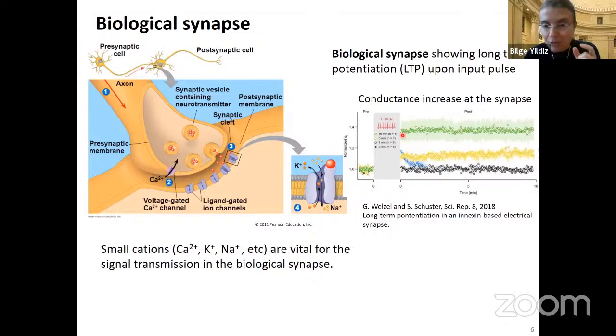So that is the green curve. The shorter that they send the stimuli, the weaker or even decaying behavior, so the loss of that strengthening, that's evident. So that's why we need to do many homeworks to learn a concept. You have to repeat to make it permanent and not to forget the next thing, right? So that's the analogy. And this type of increase in conductance with voltage stimuli is what we call potentiation. Potentiation, that is strengthening of the synapse. And transfer and accumulation of ions, in particular calcium, is a key process apparently in this increase of the synapse strength or increase of the conductance, in ease of signal transmission.